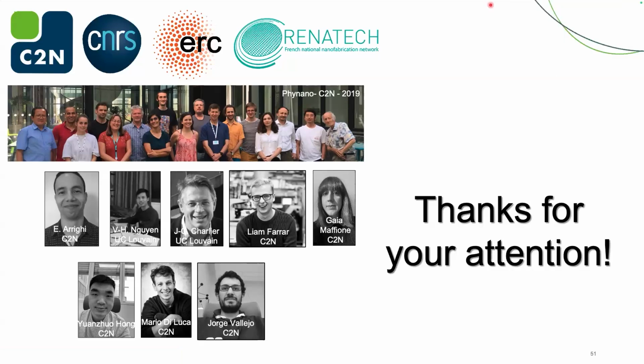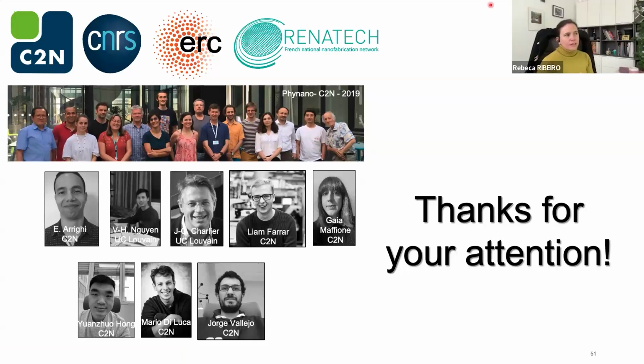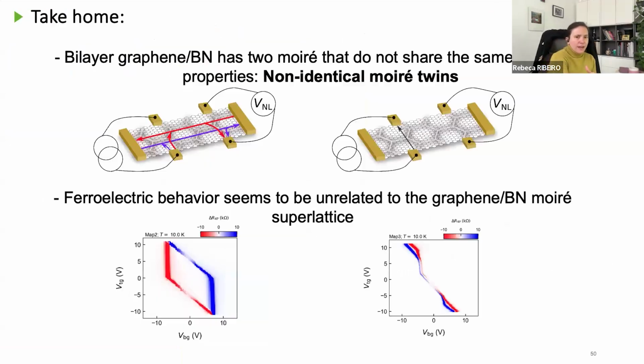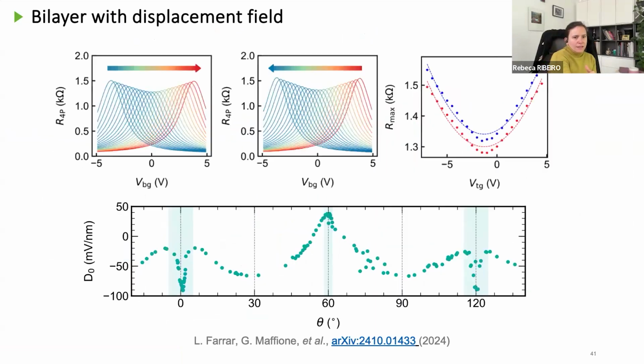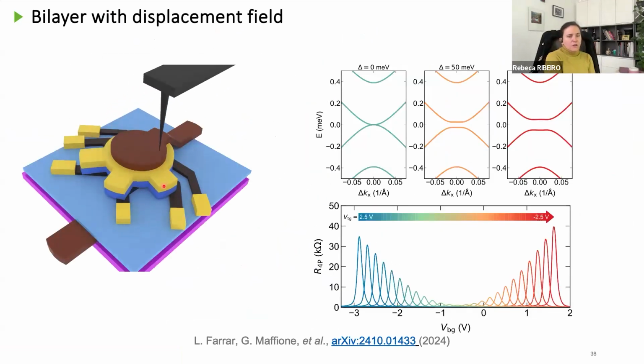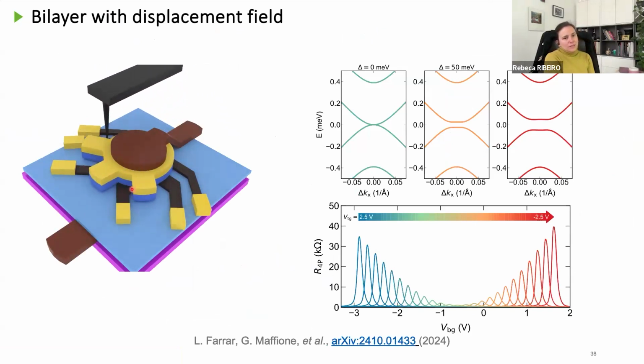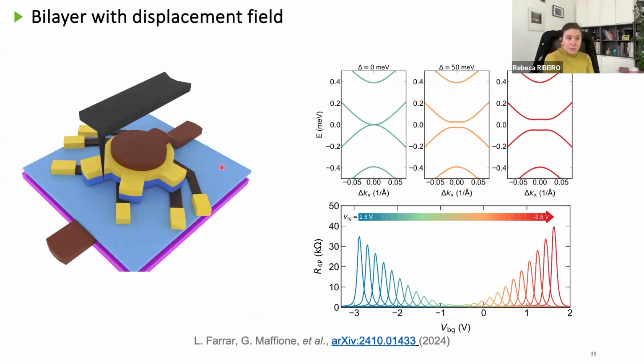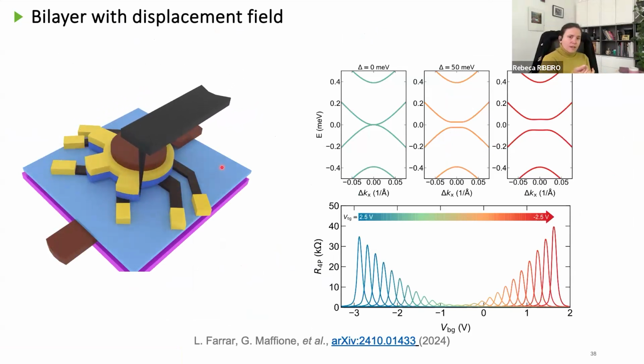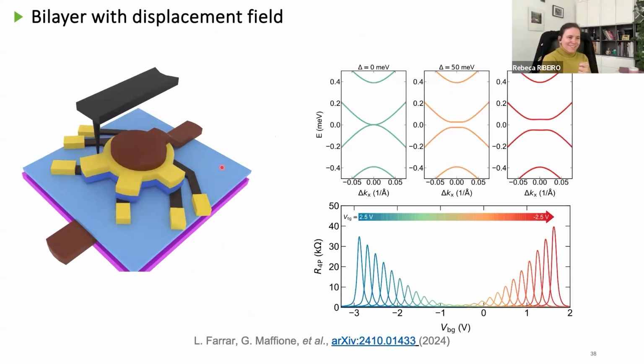That is also interesting. And so the last question is, you are showing electrical results from transport through the whole device. I was wondering if there is any information that you could get, for example, through the AFM probe using some electrical mode. If there is some information that you could get at high resolution via doing AFM on top of your graphene. Yeah, in fact, we are developing new samples right now that are the equivalent of the top gate samples, but with very thin boron nitride and with platinum instead of gold to measure the ferroelectric response, to see if it's a real ferroelectric response. So yeah, we are gonna use our wonderful AFM for that.